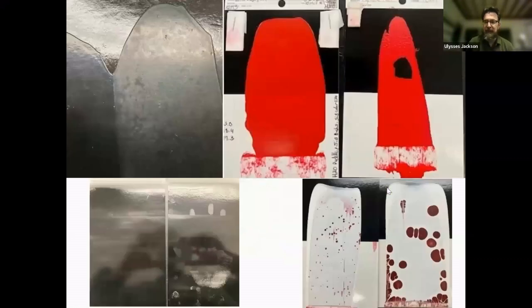Other things we have to look out for are all of the squirrely effects that artists would not want to see. So this top left corner is an example of surfactant bloom. On the left side here, there's this nice jet black coating. That would be our standard. This is made out of a dispersion that another company said, why are you making your own carbon black dispersion? Use ours. It will be way easier for you. And you can see that after a few months, it bloomed with excess surfactant coming out. That surfactant stabilizes the water-based paint while it's wet, but then it kicks out as the paint cures because it's no longer needed, and those hydrophobic tails can come out of the surface.